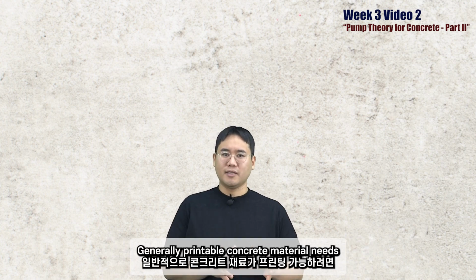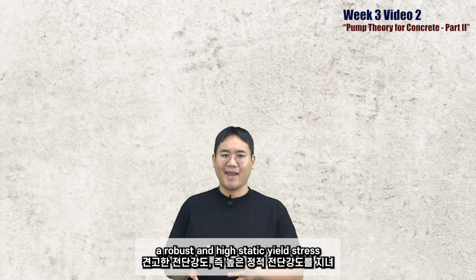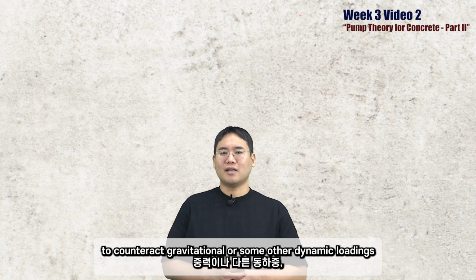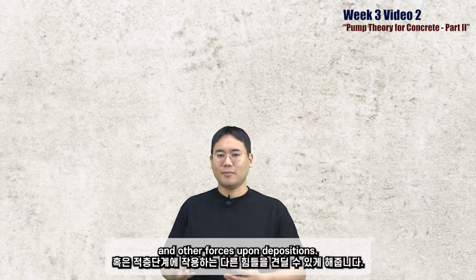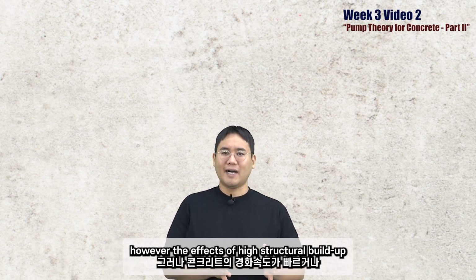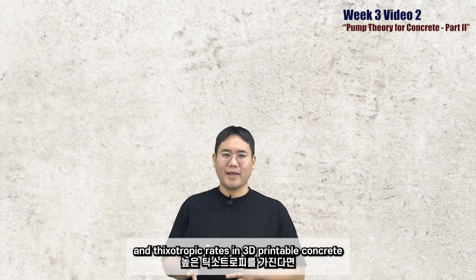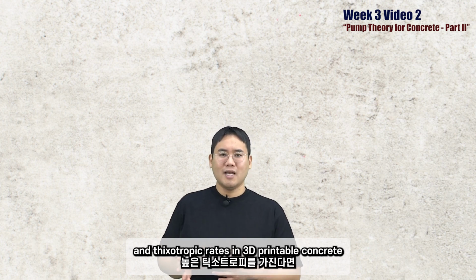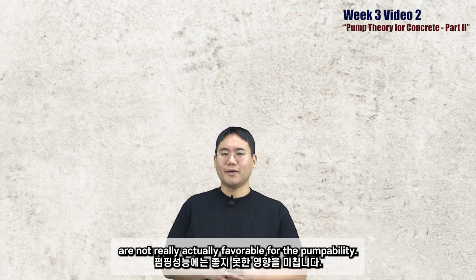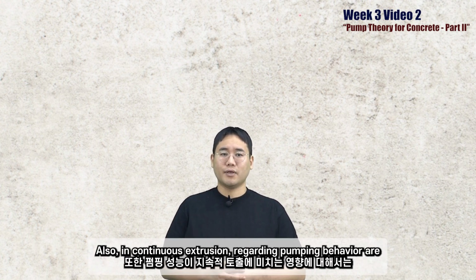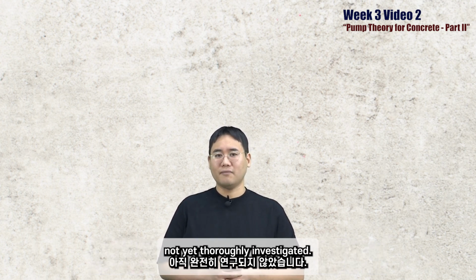Generally, printable concrete needs a robust static high yield stress to counteract gravitational and other forces upon deposition, like dynamic and some other forces. However, the effects of high structural buildup and thixotropic rates in 3D printable concrete are not really favorable for pumpability. And also, the pumping behavior in interaction with them is not yet thoroughly investigated.